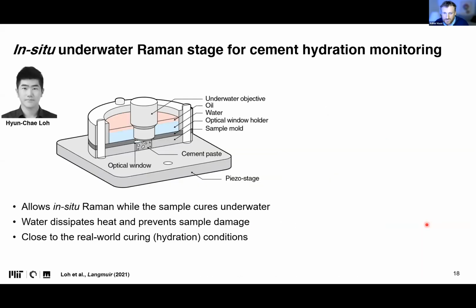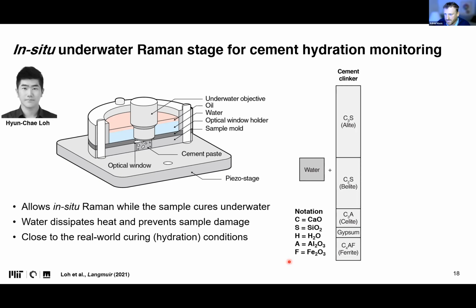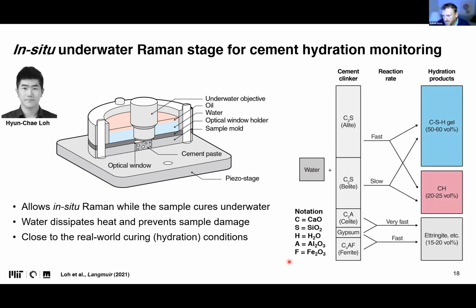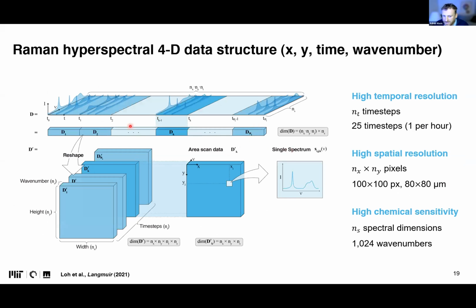Okay. So this is the student that spent a lot of time nailing down all the experimental details to efficiently use Raman spectroscopy, a confocal Raman microscope, to do in situ Raman while the sample is underwater. Turns out that this water is really cool because it dissipates heat, potential heat that is created by the laser interacting with the sample, and indeed, I said that it's close to real-world conditions. And what we can do is monitor most of the initial chemistries and then also eventually understand the hydration products. As I said, Hyun-Chae definitely spent some time developing the method that is outlined in this paper.